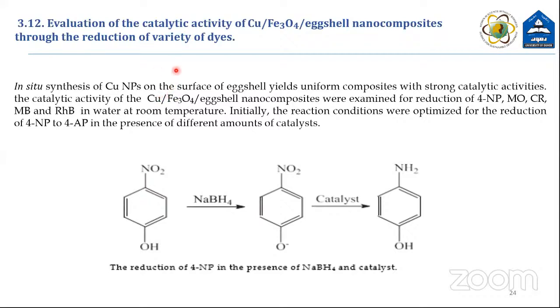To evaluate the catalytic activity of the copper magnetite eggshell nanocomposite through reduction of a variety of dyes in situ, the synthesis of copper nanoparticles on the surface of eggshell yields uniform composites with strong catalytic activity that can reduce some dyes, like, for example, we have